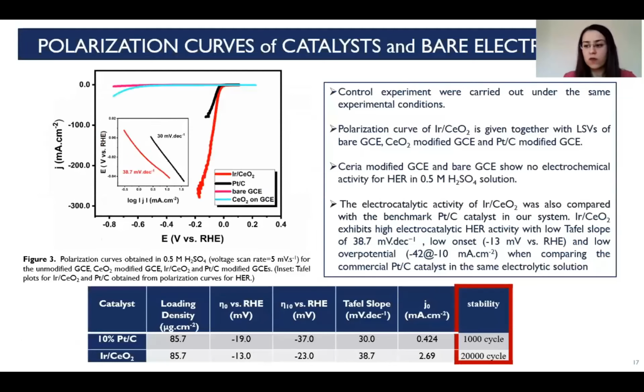Linear sweep voltammetry was used to investigate the electrochemical activity of modified electrodes in 0.5 molar sulfuric acid solution at 5 millivolt per second scan rate. Control experiments were carried out under the same experimental conditions, and the polarization curve of the iridium ceria is given together with the linear sweep voltammograms of the bare glassy carbon electrode and ceria modified glassy carbon electrode, also the commercial platinum carbon electrode.